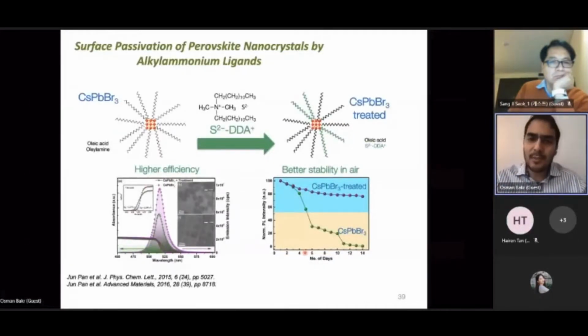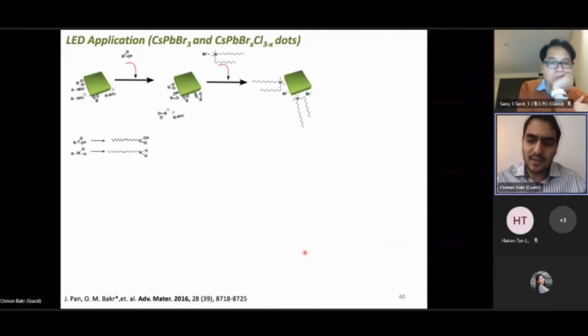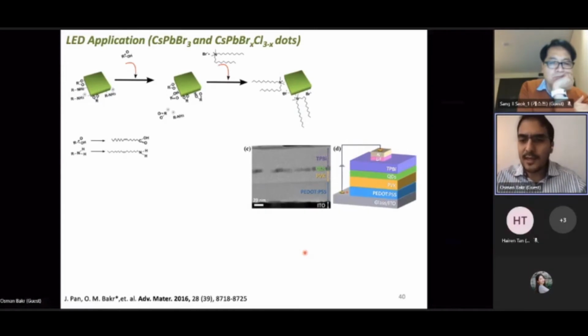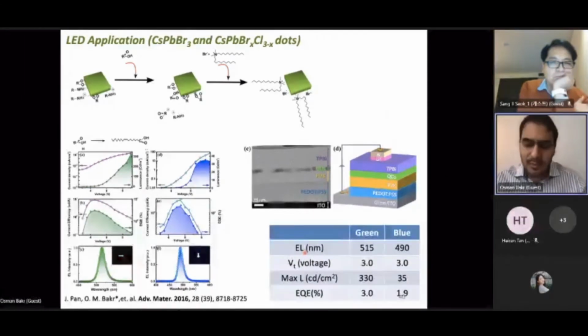And so what we tried to look at is, can we apply ligand exchange methods to replace the native ligands like oleic acid and oleylamine? We started with alkyl ammonium ligands, and when we replaced oleic acid and oleylamine with alkyl ammonium ligands, the stability of the nanocrystals jumped quite a bit, and if we made devices from these materials, we had a significant jump in electroluminescence. These numbers sound modest, but in 2016 they were quite high for LEDs based on perovskite nanocrystals. In fact, 1.9% EQE was a record for blue perovskite LEDs. Of course, the field has jumped since then and is much more advanced, and people figured out how to stabilize perovskite nanocrystals for LEDs as well.